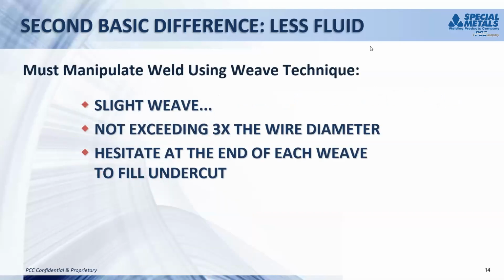So what we have to do, instead of turning the amps up, is use a weave. It should not exceed 3 times the core wire diameter. So if you're running a 1/8 inch rod, then you don't want to weave more than 3/8 of an inch. And the main thing, very important, is to hesitate at the end of each weave to fill in the undercut. And we'll show you a picture in just a minute.